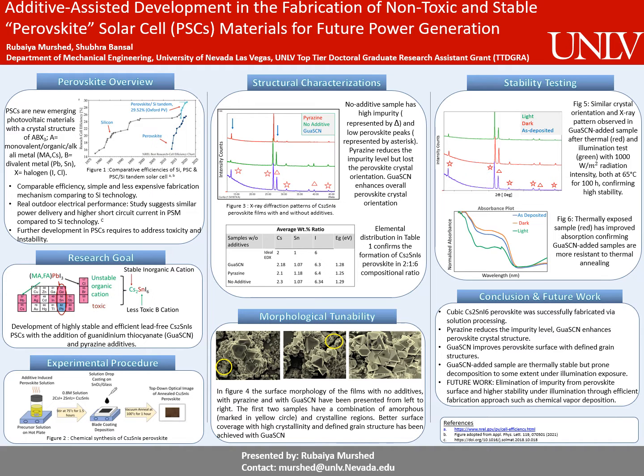If we focus on the second arrow, we can see that the intensity of the impurity peak has been significantly reduced by the addition of pyrazine. Our elemental distribution in table 1 shows that all of our samples have a ratio close to the ideal composition ratio of 2:1:6 for dicesium tin hexaiodide perovskite.